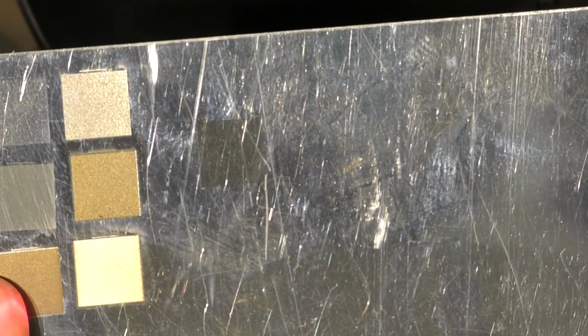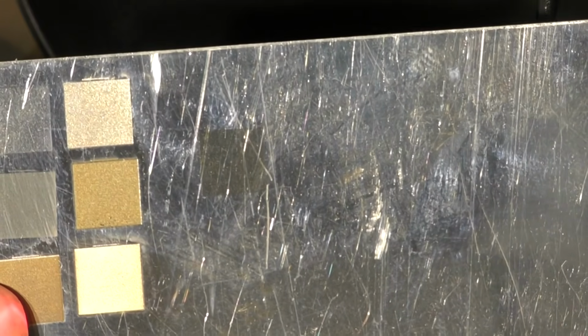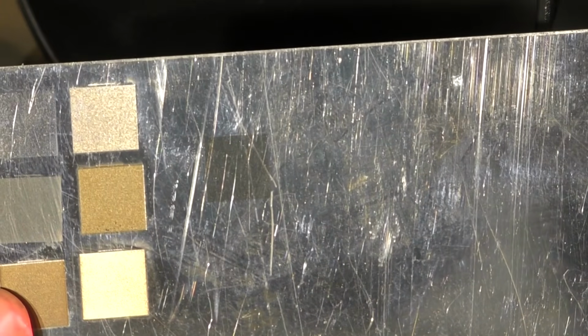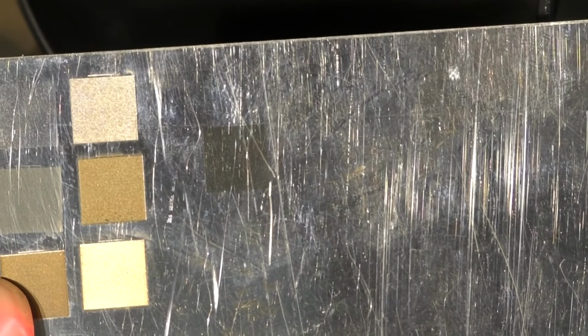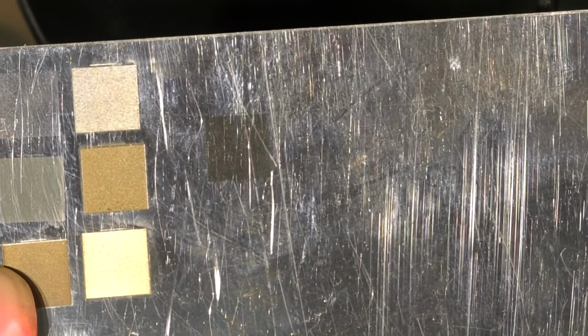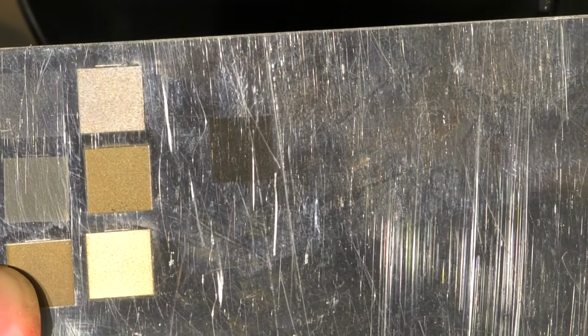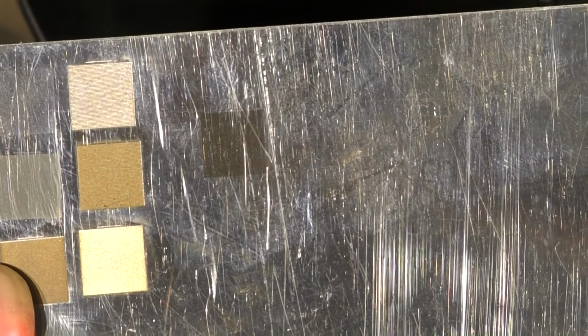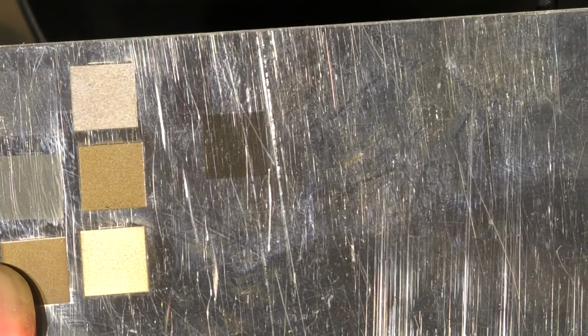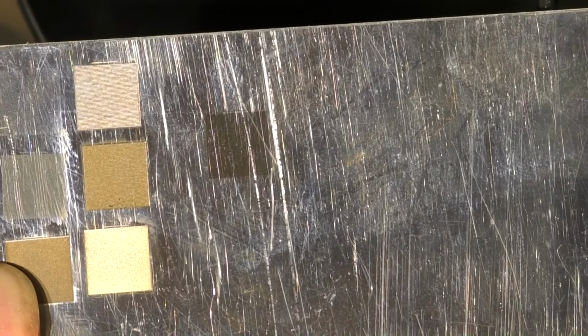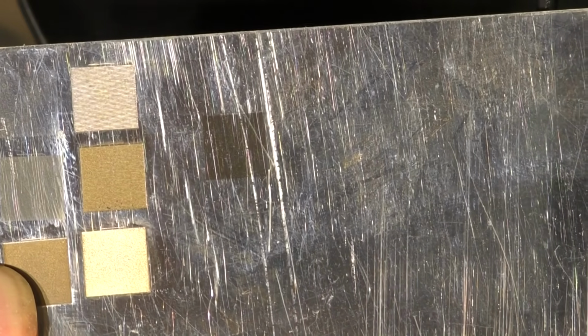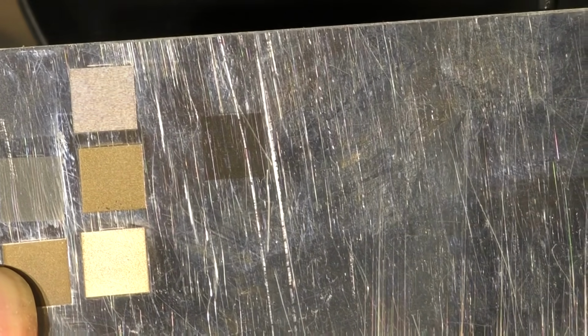So I think that demonstrates to you clearly that changing the power ratio in one direction is not exactly the same as changing the power ratio in the other direction. There are differences. We get more effective heat change by horizontal change than we do by vertical change. And that's an important lesson that I learnt when I was hunting for these colours. So these very coarse, glittery colours, as you can see, are much more resistant to light change.